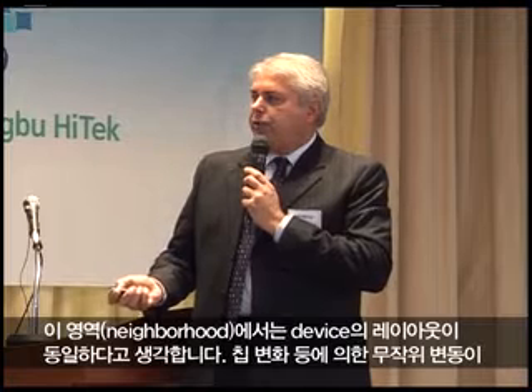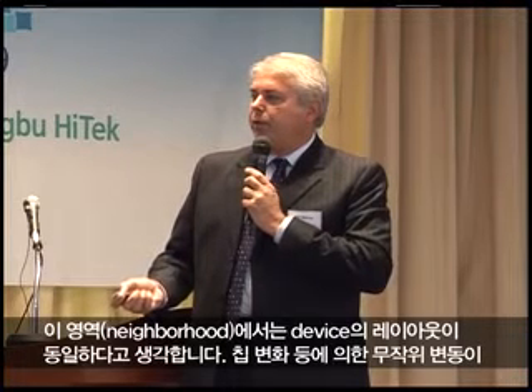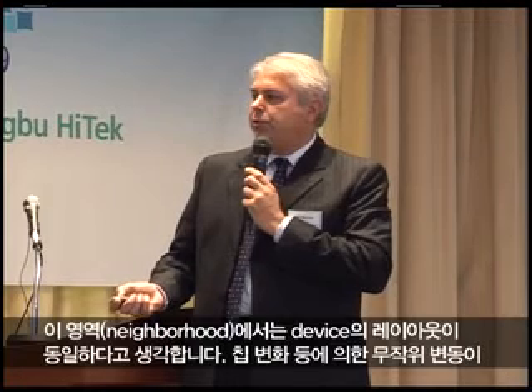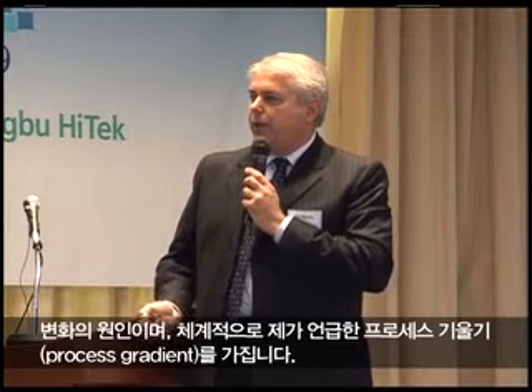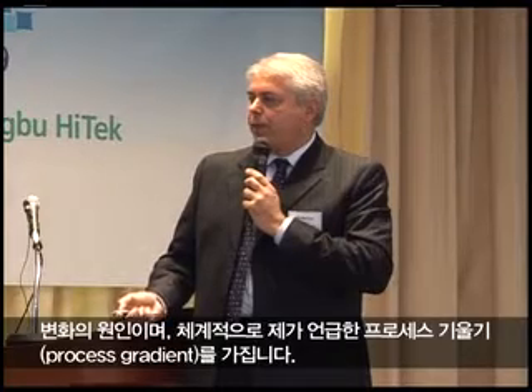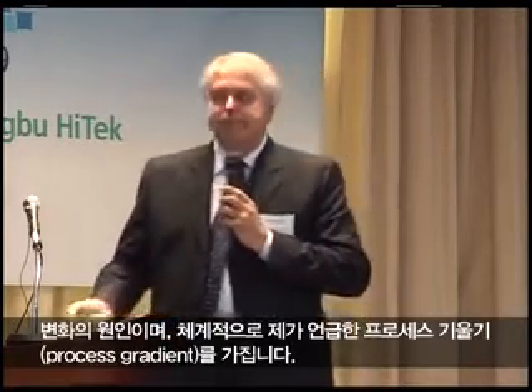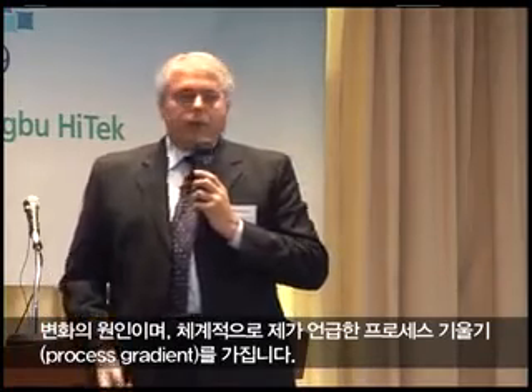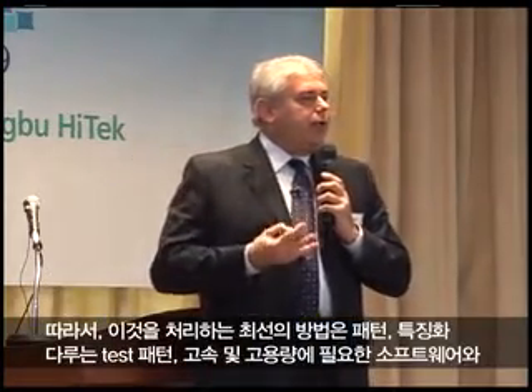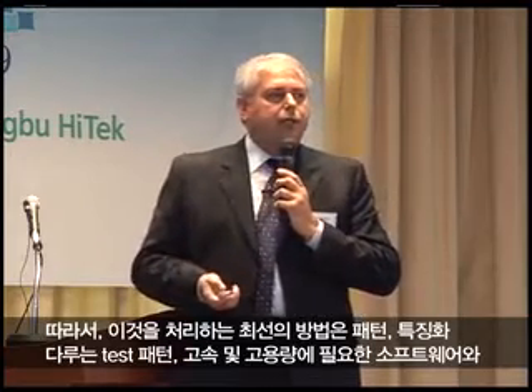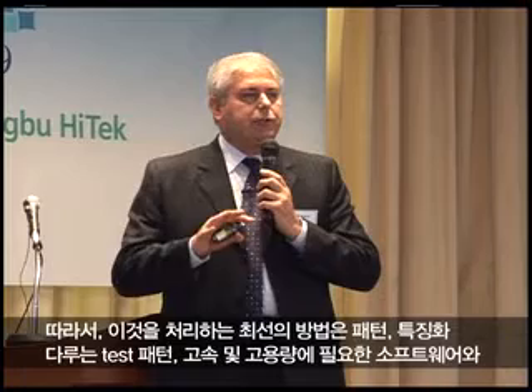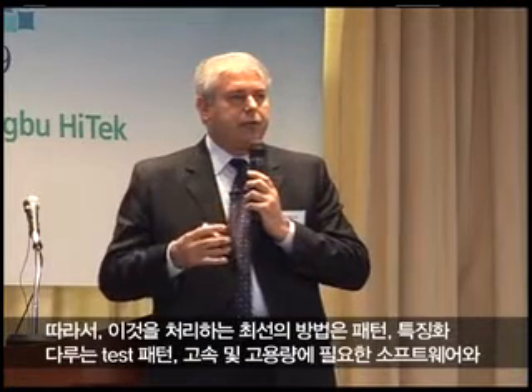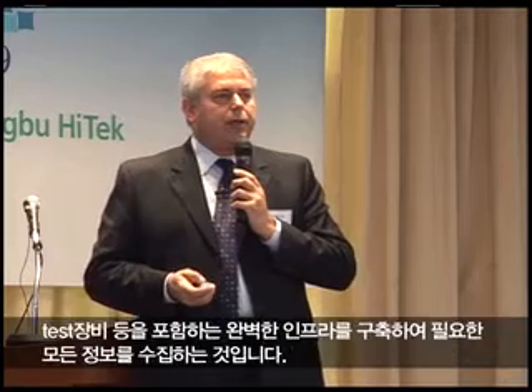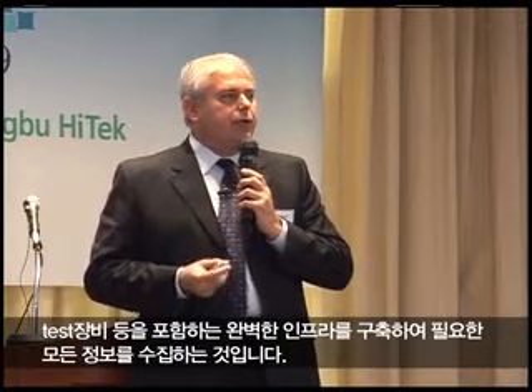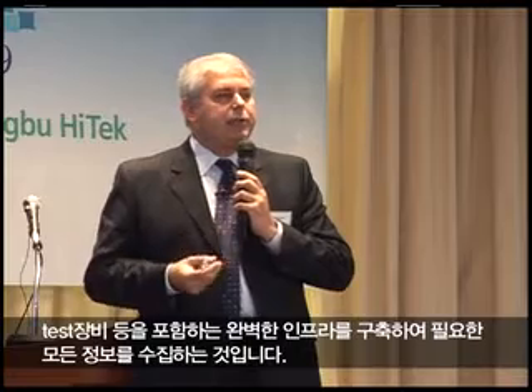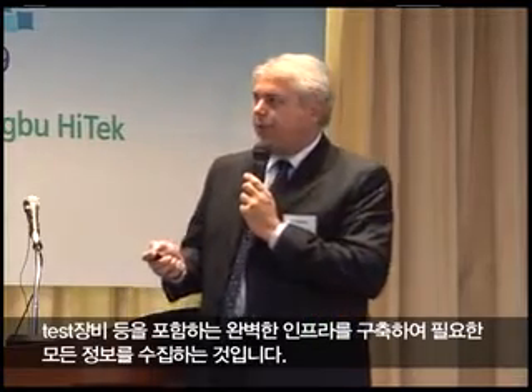We think that for devices of identical layout and neighborhood, we have these sources of variation: random dopant fluctuations, across-chip variation, and so forth. And systematically, we have process gradients that I had mentioned. So we feel that the best way to get a very good handle on this is to have a very complete infrastructure that includes the test patterns to take care of the characterization, as well as the software and the test equipment necessary, at high enough speeds and high enough capacity to capture all the information that's necessary.